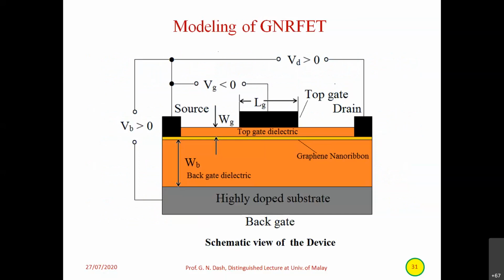So we have a highly doped substrate of silicon, which is serving as the back gate also, and then a thick layer of dielectric over the substrate. The dielectric width is WB, that is the thickness of this. Then the graphene nanoribbon, the yellow line, is put over the dielectric, then over the graphene another layer of dielectric, which has a width of WG. And this is the gate metal, this is the source contact, and this is the drain contact. And there are two gates. One is called a top gate, of smaller length, and the back gate covers the entire length of the graphene nanoribbon.